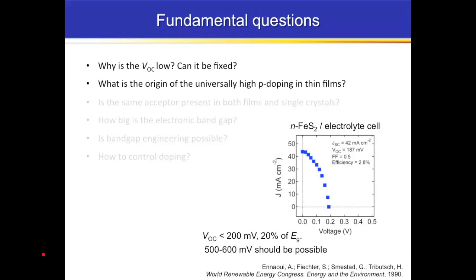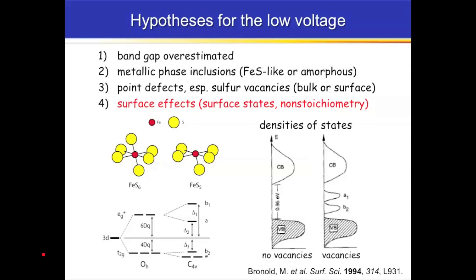So let me first prove to you that the voltage of pyrite is actually quite a bit lower than it should be. This is the record, the champion device from 1990, actually. This is Helmut Tributsch's group, did most of the work in the 80s and 90s. And what you see is very large short circuit current, equivalent to what silicon can produce, but a VOC that's about 0.2 volts or less. And that's about 20% of the band gap, and really what we should be able to get out of pyrite is something between 500 or 600 millivolts. And so we've got about a factor of 3 too low in voltage here, which is, of course, killing the device efficiency.